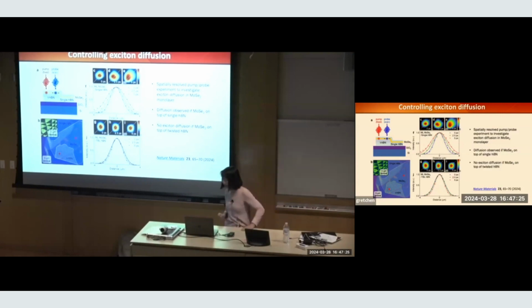Charge transfer. Yeah, I think I missed. So it's within a single layer. Yes. That's what we believe. Oftentimes this picture, interlayer exciton with an electron in one layer, holding the hole in the other layer, is a simplification. These layers are 0.3 nanometer thick. The wave function can certainly extend to the other layer. Most of the time, it's a bit of a hybrid. Maybe the hole is more delocalized or the electron is more delocalized. So you have a funny distribution of the electron hole wave function.